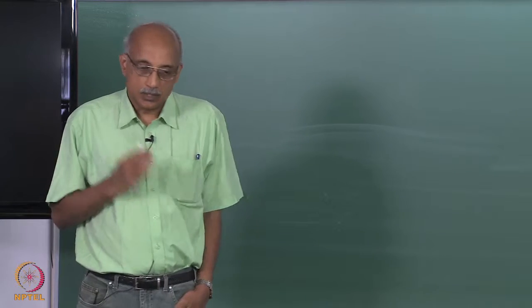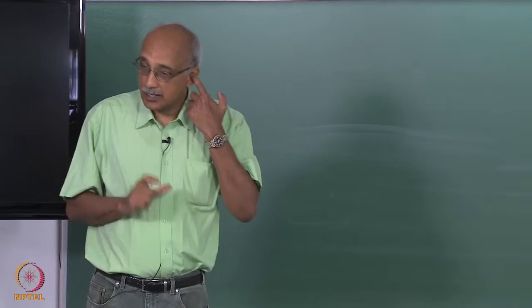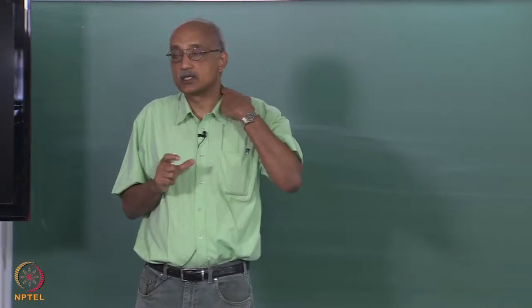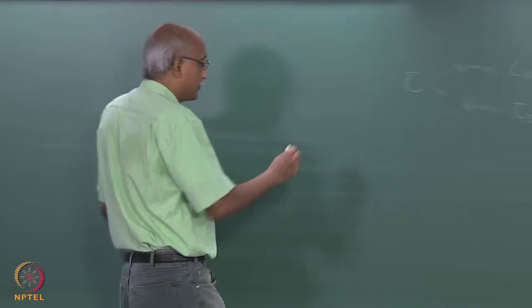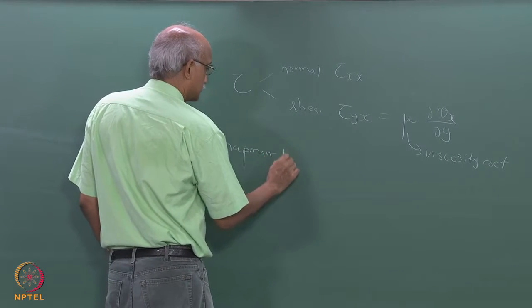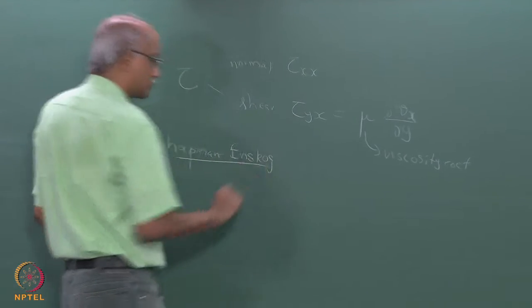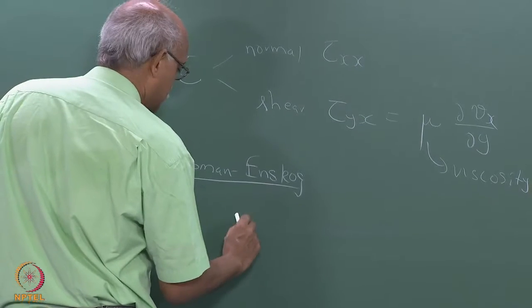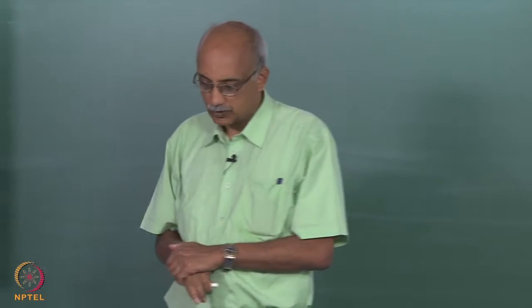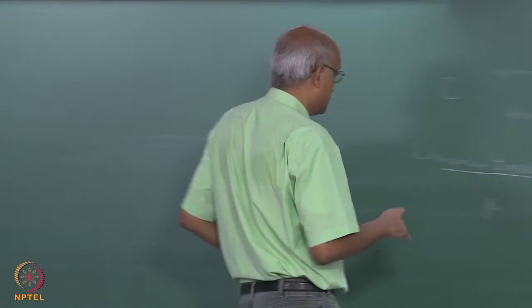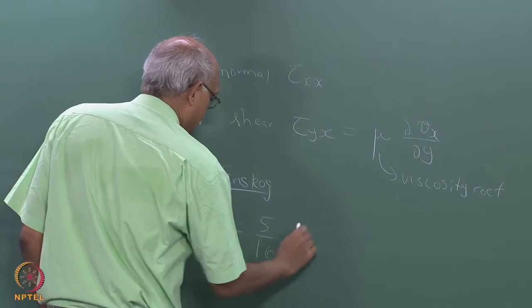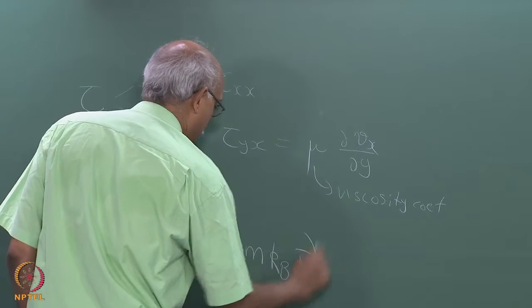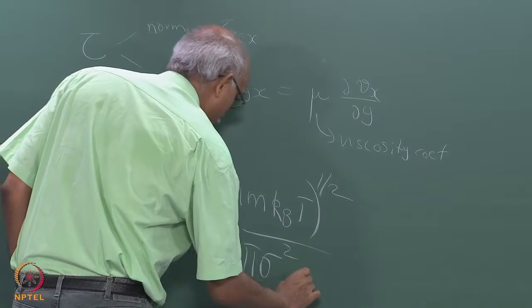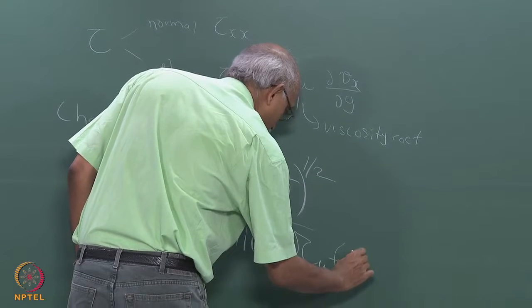So, in constitutive laws, the constitutive coefficients can be derived either theoretically from first principles or phenomenologically from observations of experiments. I am sure you are familiar with the Chapman-Enskog theory. Have you read that in your fluid mechanics, Chapman-Enskog, which says that for viscosity, particularly of low density gas, mu can be related to the other properties by the following equation: square root of pi m kBT over pi sigma squared omega mu, which is a function of kBT over epsilon mu.